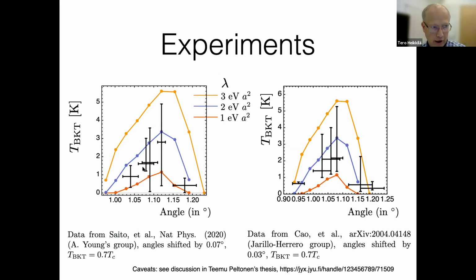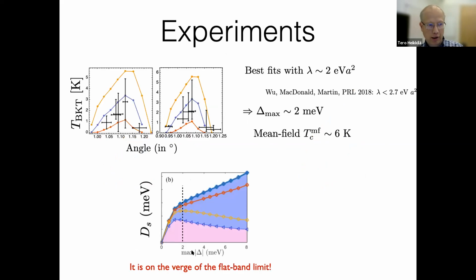And here is a comparison of our results to experimental values of BKT temperatures as a function of angle from two experiments, and they seem to match pretty well to lambda being 2 electron volts times a squared, where a is the graphene lattice constant. Now from here we can estimate how large the delta would be in this system, because this is not directly accessed in the experiments. It would be of the order of 2 milli-electron volts, which would correspond to a somewhat higher mean field critical temperature. The BKT temperature is smaller.